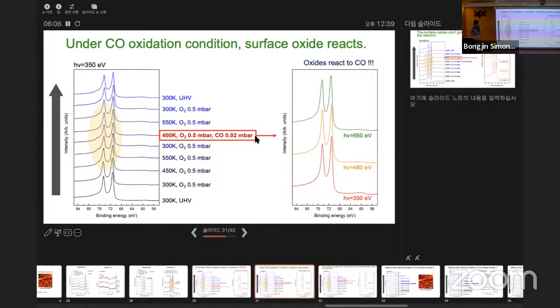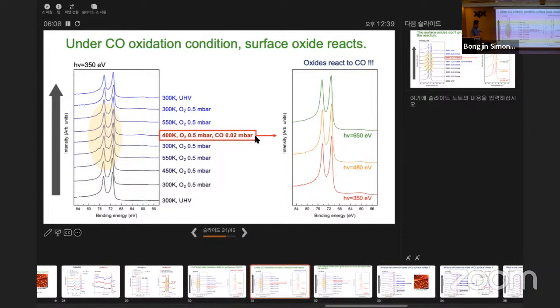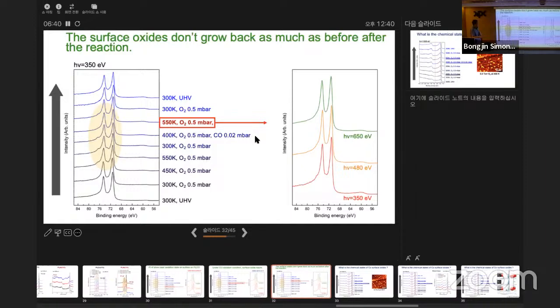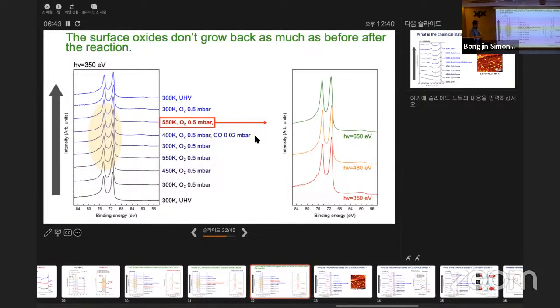And then when we put the CO, we witnessed this from here too, but we wanted to confirm that when we introduce the CO interacting with this oxygen, 0.02 millibar, we start to see clearly that this oxide that was attached to the platinum is all gone. In the metallic state, it was always clean. So from surface sensitive to bulk sensitive, everything now becomes clean. That means the oxide actually reacted with the CO. That's something that we see.